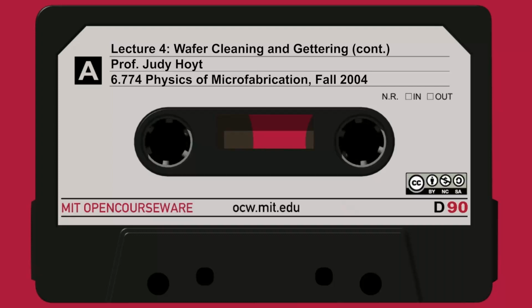This is a machine that takes a laser and scans it across the surface of the wafer, and it looks for spurious reflections. Every time you hit a particle, you no longer have specular reflection, and it notes that. And it says, aha, there must be a particle, or what they call a light point defect, LPD. This is to prevent having to have people sit in the clean room and literally count the particles on a wafer. That would be too tedious and inaccurate.